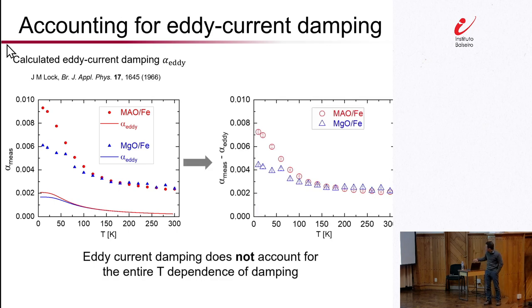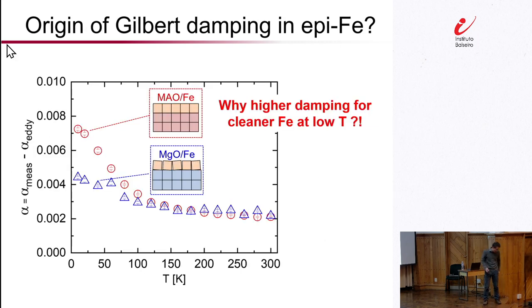So you can then, of course, subtract out the eddy current damping from the total damping, and we still end up with qualitatively the same experimental trend. Right, so the intrinsic damping continues to increase with decreasing temperature, even more so for the cleaner sample. Okay, so we're essentially back to where we were just a few minutes ago, still wondering why we are seeing higher damping in the cleaner sample at lower temperatures.